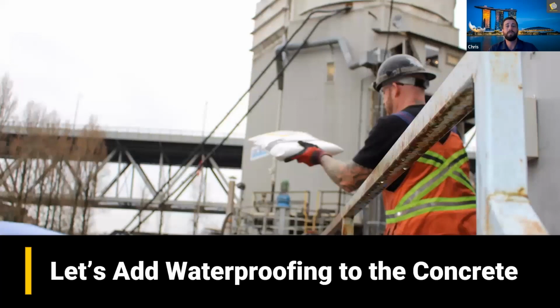Yeah, and it's easy. What do you do? You add waterproofing to the concrete. It's really as simple as it looks. One bag per cubic yard is added to the mixer truck right in the batch plant. Crystalline admixture becomes a permanent part of the concrete matrix and will hold back up to 460 feet of hydrostatic pressure. This turns your concrete into the membrane, and solves the issue of permeability at its core.